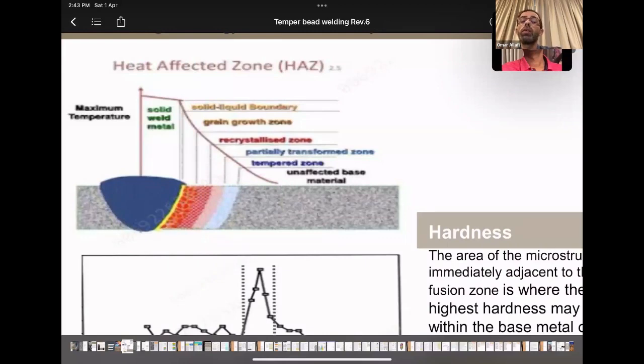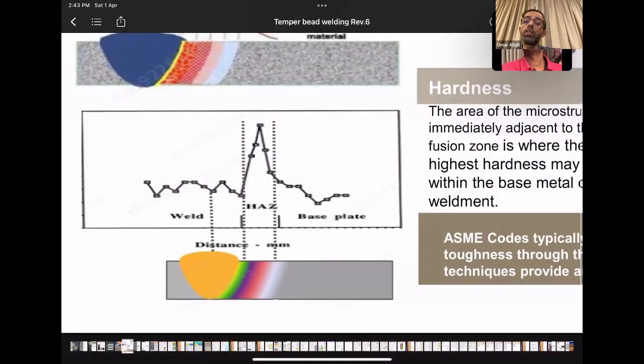This, of course, is because it goes above the transformation critical temperature, and there is a phase change from ferrite to austenite, and upon cooling, the martensite will form, and upon heating, the grain size will enlarge. So this enlargement in the grain size will affect the toughness, and the fast cooling or formation of martensite can result in high hardness values. As we can see here, this is where the maximum hardness can occur, just near the fusion line of the weld.